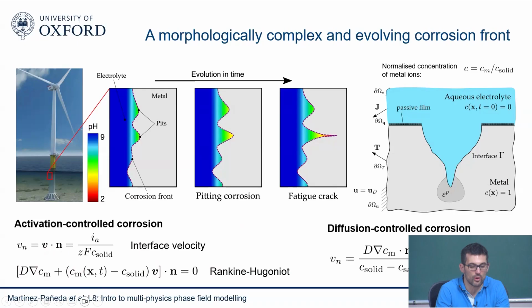And then when you have diffusion control corrosion, what happens is that you have saturated your interface with metal ions. So you need those metal ions to go away before you continue to corrode your sample. So the concentration of metal ions at the interface is given by this Dirichlet boundary condition, the saturation concentration, which is a material property that we know. And then the velocity of the corrosion front is obtained by the Rankine-Hugoniot condition, just by substituting the saturated concentration. So you can see here why modeling this will be very challenging. You have Robin and Dirichlet boundary conditions that are changing in both time and space. You have an evolving interface where you need to prescribe Robin and Dirichlet boundary conditions that are evolving in time and space. So this is essentially a mathematical nightmare.